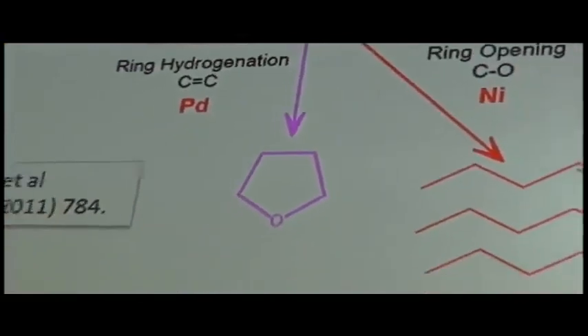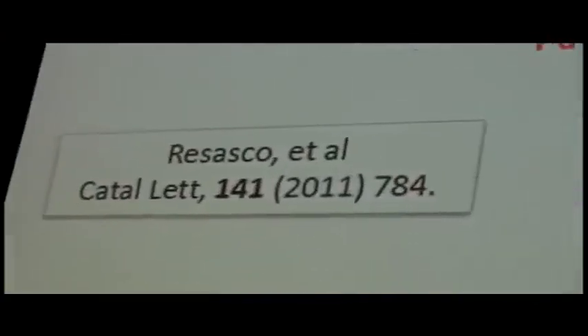Okay, and those can lead to some improvements or changes, at least, in the selectivity of the catalyst of those materials. One of the reactions we're interested in for biomass processing, which has been highlighted in many talks here this week, is the reaction of furfural to furfuryl alcohol, which is just a hop, skip, and a jump to levulinic acid, okay, which is an important intermediate for fuels formation there. We can form furfural, we can react furfural to various components, such as furfuryl alcohol, which is our preferred product shown on the left here, or if we concentrate on more palladium catalyst, we'll decarbonylate that material to go to furan as the product. We're very interested in improving the selectivity to the furfuryl alcohol in this material here.